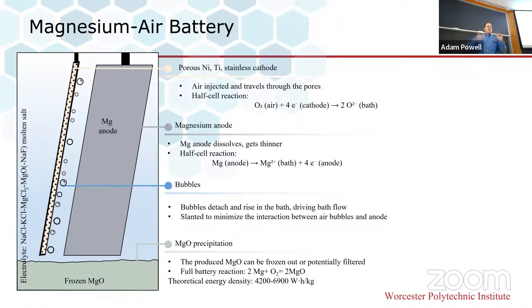We were able to see an immediate jump in the voltage due to a reduction of the magnesium oxide concentration and activity in the molten salt. So it was really exciting. And waiting for something to go wrong, and I shouldn't say that. Everything has gone pretty well so far.